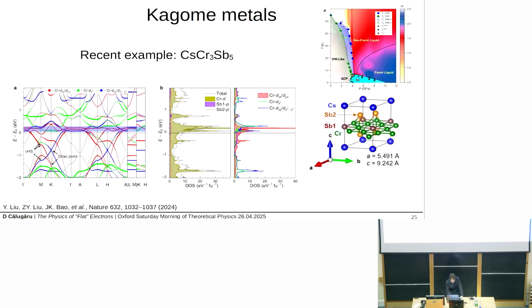As shown here on the phase diagram on the right, the system exhibits very robust superconductivity as I apply pressure. Directly above this superconducting phase, the system is in a non-Fermi liquid state. Now, how do I know it's a non-Fermi liquid? Well, experimentalists can actually measure the resistance of a sample, right? And if the system is a Fermi liquid, then the resistance should vary as T squared, where T is the temperature. So whenever you see a different exponent, and this is really what's being plotted here, you know that it's a non-Fermi liquid. So this is very interesting.